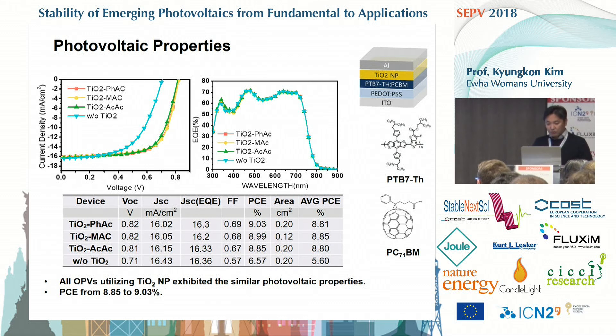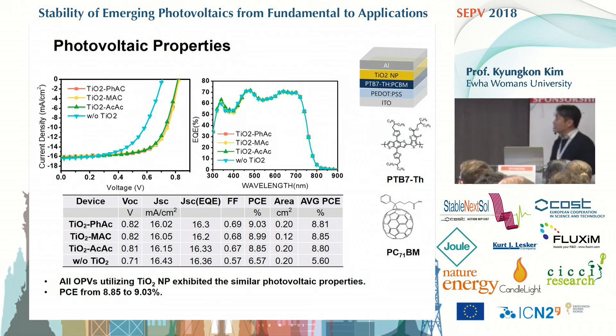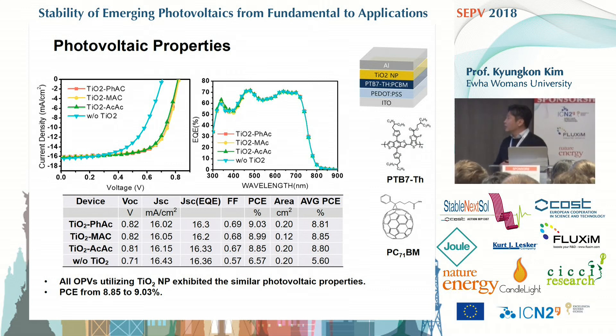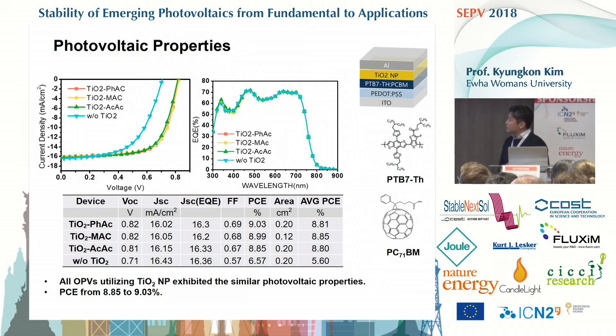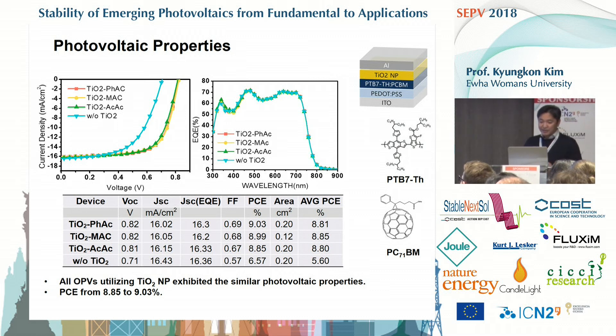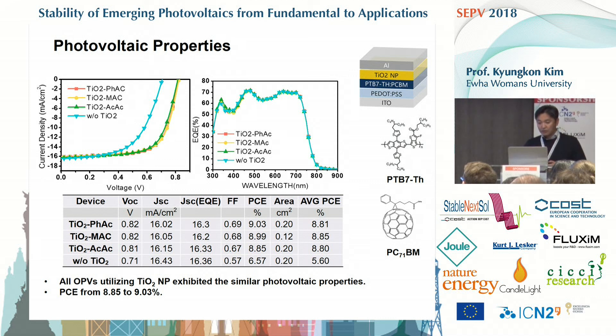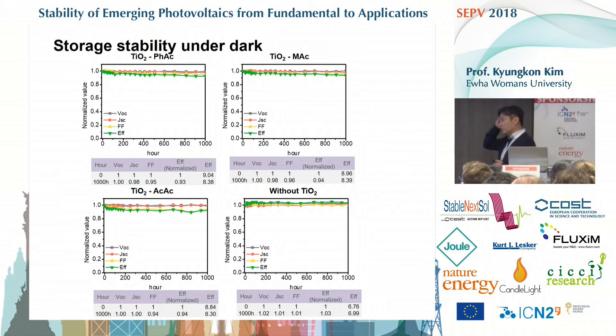The performance of these nanoparticles is similar regardless of the type of organic stabilizer — they show fairly similar performance. It is better than the device without titanium dioxide, especially in VOC. We have tested this device under one sun light intensity after encapsulation with a glass cap, using this material, and we monitored the efficiency change as a function of time.